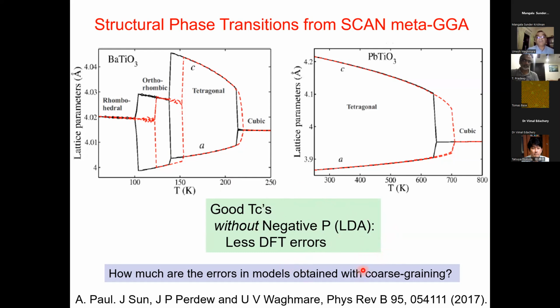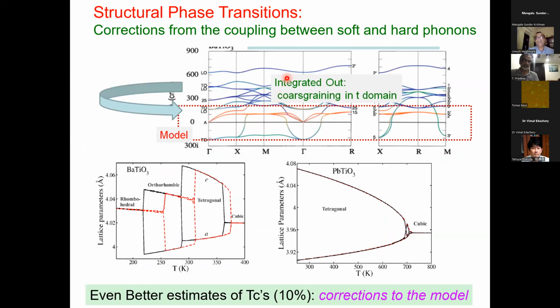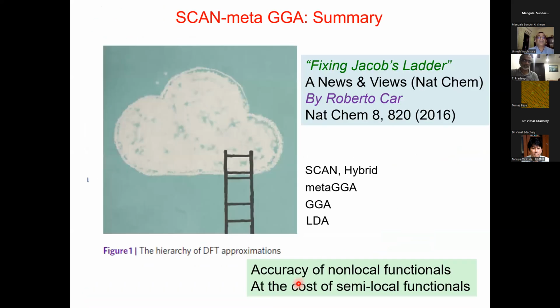And then one asks the question, is the rest of the errors due to coarse graining? Coarse graining meaning we are eliminating these high energy phonons, so they can couple anharmonically with unstable phonons. And we calculated those corrections, and we find even better estimates in TC, like 10% corrections to the model that we developed. Okay, so this is sort of the state of the art.